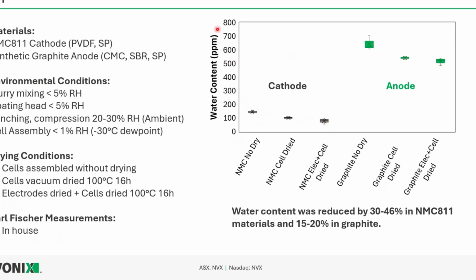And anodes retain moisture a lot more than the cathode materials. These are also coated with water in the slurry. But again, we're able to reduce the amount of moisture in the anodes. So what's the effect of this? It's a fairly small difference in some of these cases. Can we see the effect of this? Does it really matter in cell performance?